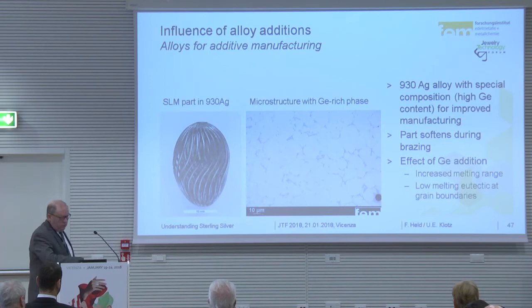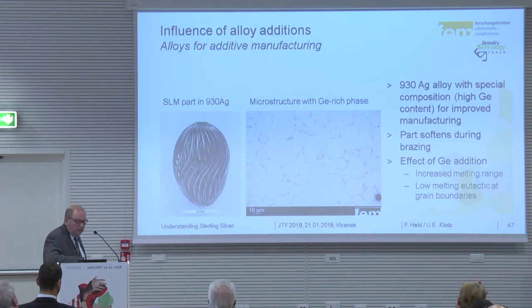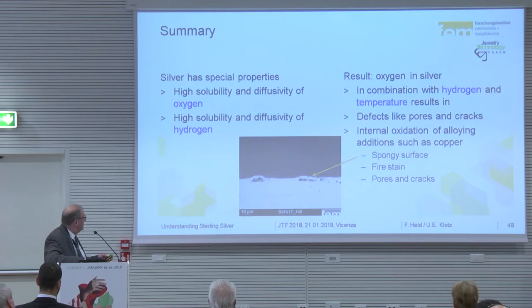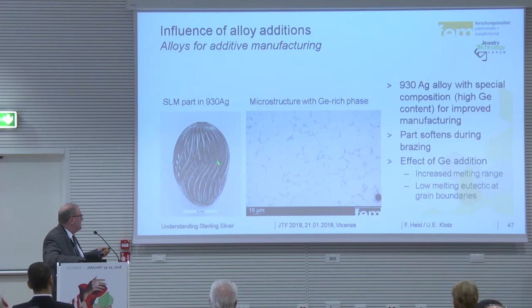Influence of alloy addition. We got a part from a partner in a research project. This was done by selective laser melting in 930 silver. And he wanted to make some annealing. He made the annealing with a normal hard soldering material, which means a melting temperature of about 780 degrees. What happened? The part changed the contours.